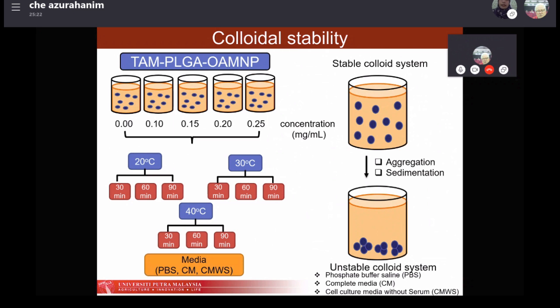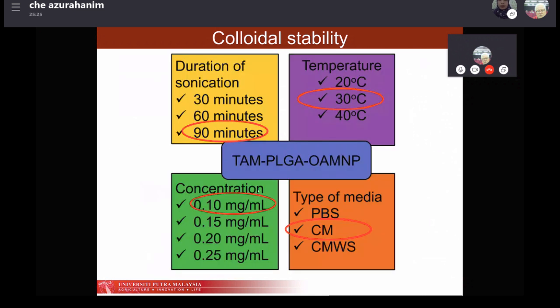Okay, so from her study, she found that when we prepare the TAM-PLGA-OAMNP, the optimized sonication time is 90 minutes at 30 degrees Celsius at a concentration of 0.1 milligram per ml of TAM-PLGA-OAMNP. And of course, in terms of colloidal stability in cell culture media, the one with serum showed the highest stability. And here are the TEM images of just MNP as well as OA-MNP. Actually, she already published this paper in February, and the other paper about 2 months ago. So here are TEM images for PLGA OA-MNP and TAM-PLGA-OAMNP.